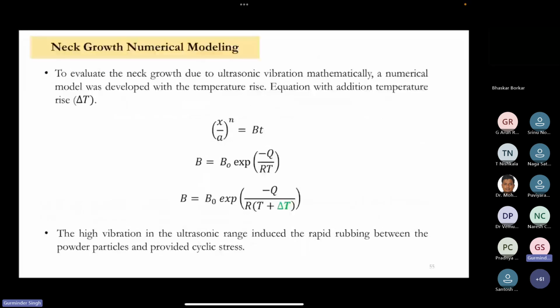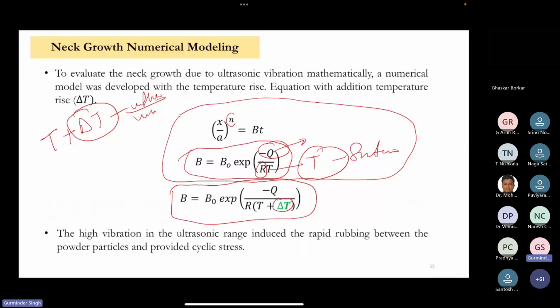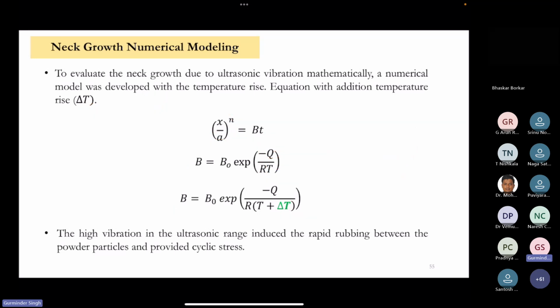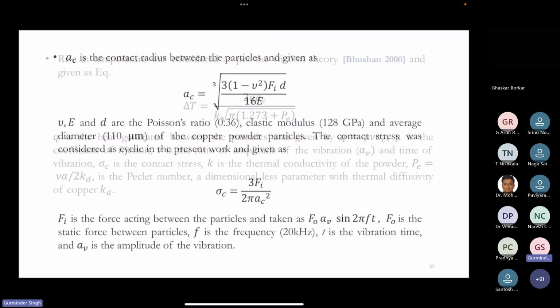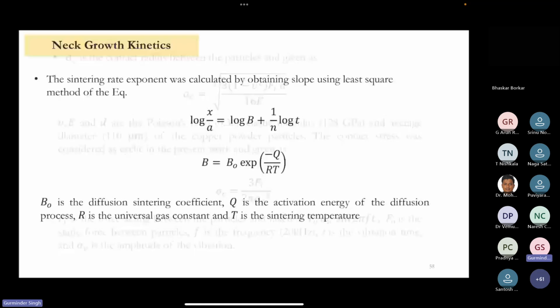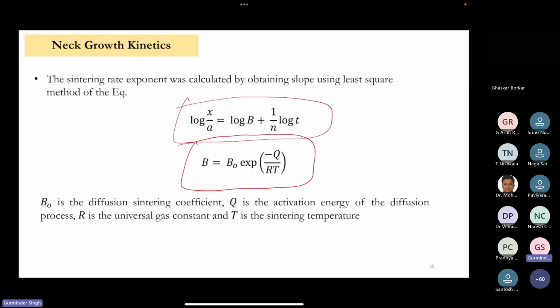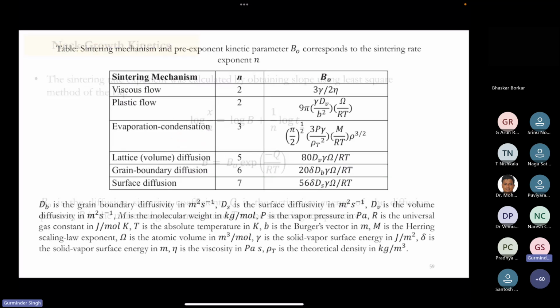This is having n coefficient and into the power. So this n, if you have both experimental values from the left hand side and the right hand side, and you fit this equation to this data, you will get the n value, which will be the slope of this equation by using the least square method. So you can find out the n value.